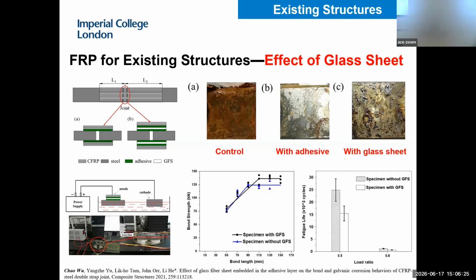So we did a lot of static testing and fatigue testing, and this is the result. The blue curve is for specimens without glass fiber in the bond line, and the black curve is for samples with glass fiber in the bond line. For static loading, our conclusion is that you can use glass fabric to avoid galvanic corrosion—it's good for static behavior, and you see improvement in static strength.